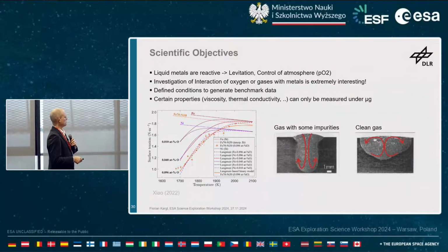What is shown here is surface tension as a function of temperature for different alloys. And you see here that pure iron behaves as expected. Surface tension goes up with decreasing temperature. If you add a bit of oxygen, the surface tension goes down significantly. And on the other hand, also the behavior changes. At high temperatures, you might still have this increase with decreasing temperature, but then you start to decrease here.